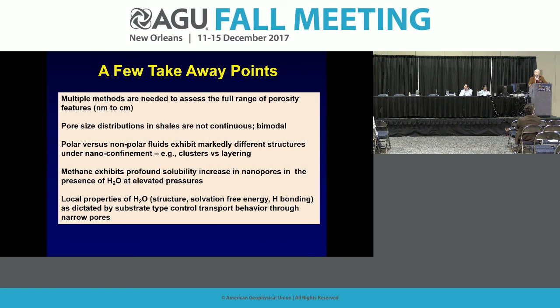So a few take-home points. First, we talked a little bit about the availability of a number of really nice methods to interrogate these materials at various length scales, 10 orders of magnitude, in fact, neutron scattering and so forth. We've touched upon the fact that in some shales, particularly the high clay-rich shales, we're getting this bimodal distribution. Polar versus non-polar fluids respond differently under nano confinement, as we touched upon. Methane exhibits this incredible solubility increase, and these local properties of water affect this outcome in a really major way in terms of considering the behavior of gases in the subsurface.